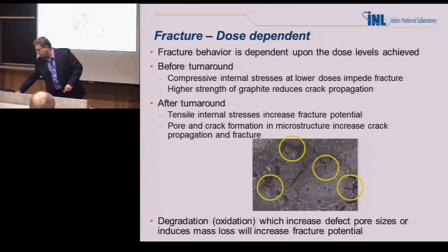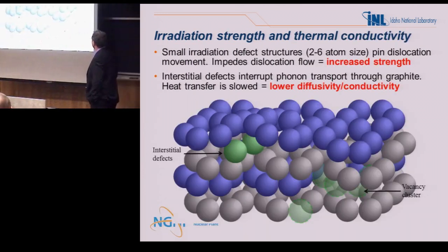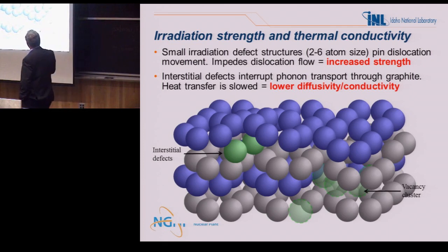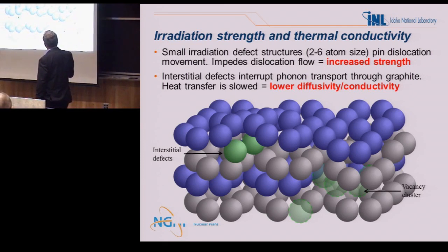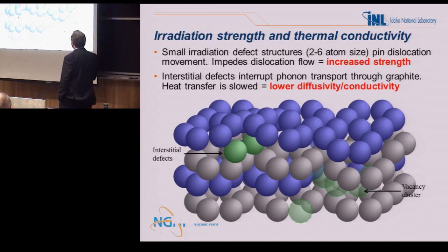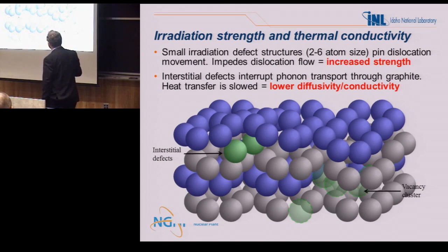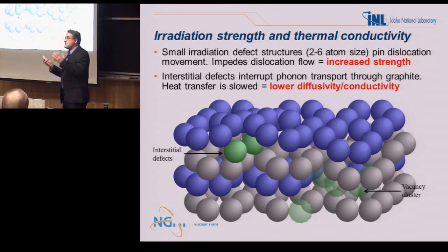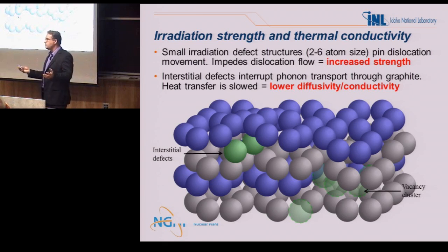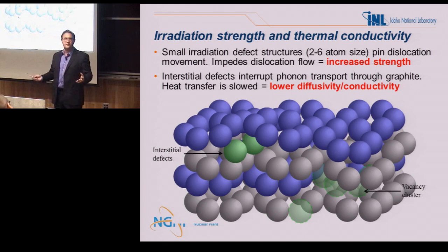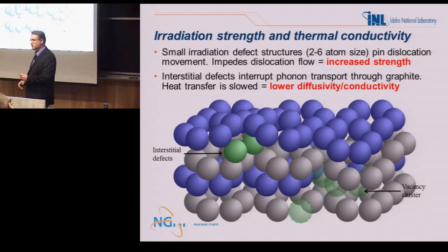Okay, and then of course the degradation of the oxidation can also lead to those types of things. I'm going to just go and real quickly breeze through this stuff because I don't want to bore you too much. But basically the irradiation strength and the thermal conductivity, what you see is these interstitial defects and the vacancy clusters. They pin any kind of dislocation movement, so it makes it stronger. And of course, the reason that it starts to decrease is because, again, you've got the pores showing up, and it just literally starts to fall apart from a strength standpoint. Thermal conductivity, the same thing. Point defects are interrupting the phonon transport through the graphite.